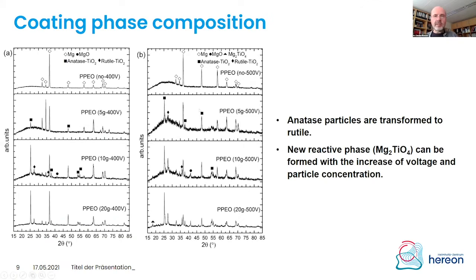If we are looking at the phases, you can clearly see from the standard electrolyte on the top, 400 on the left and 500 volts on the right side. If we're looking first at the 400 volts, you see that with increasing amount of particles added, we see them also in the diffraction patterns. First the anatase peak comes in, but you see also with higher energy and more anatase added that the rutile peak is coming in the diffraction patterns.